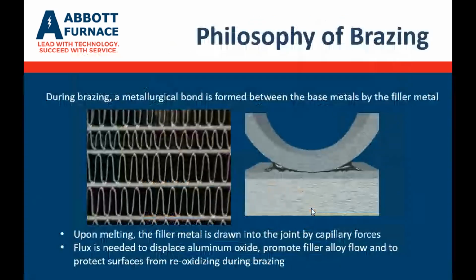So the philosophy of brazing is a metallurgical bond between the base metals by the filler metal. So we're melting the filler metal. It's beginning to flow into the joint that you can see in the right side picture. And if everything is done correctly from the fluxing and cleaning and heating, that liquid fillet will flow and fully fill that joint, making it a very hard and contact joint.